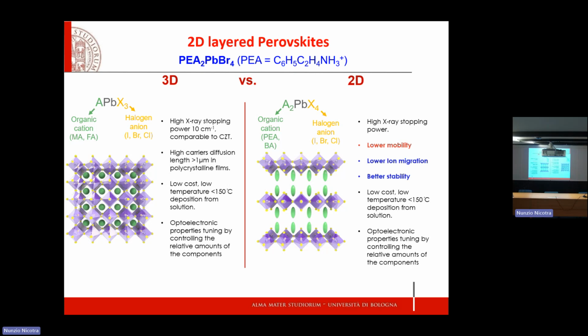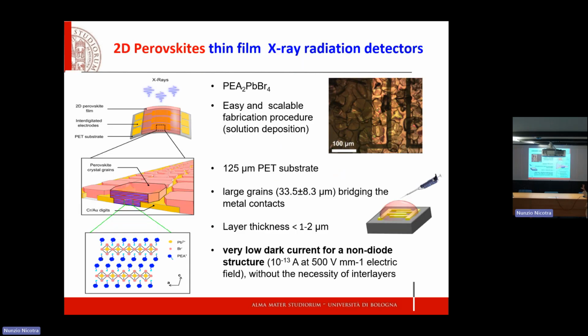Ion migration is what happens when you apply even a small bias to a perovskite film, and typically you start seeing these ions moving, and eventually the structure gets disrupted and the film stops maintaining its properties. So 2D perovskites are much more stable, even if they have a lower mobility. So basically, we started checking how their behavior as radiation detectors was. And here is, again, a solution-deposited polycrystalline film, with a thickness of about 2 microns, but we were happy to use it because it has a very, very low dark current.